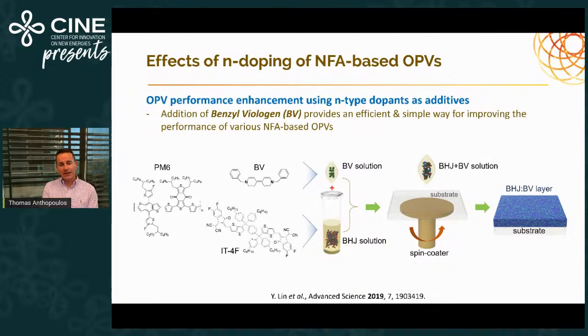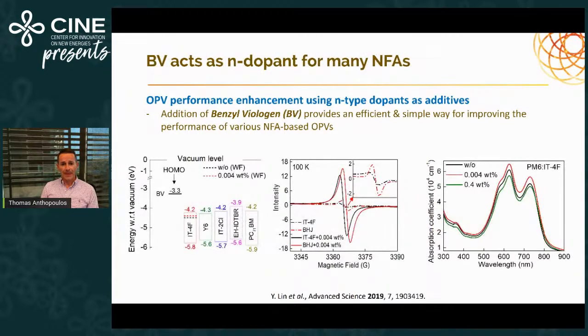So what we did in our case, we took some of the state-of-the-art bulk heterojunction materials, and we started screening a number of dopants. At the time, we'd been working on this benzyl viologen, BV, a known N-type dopant in the organic and inorganic world. So essentially, we took small amounts of it, we introduced it directly into the formulation of our bulk heterojunction and spin coated it on top of the ITO electrodes.